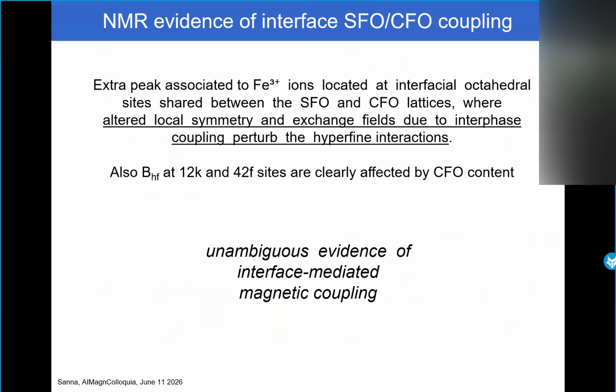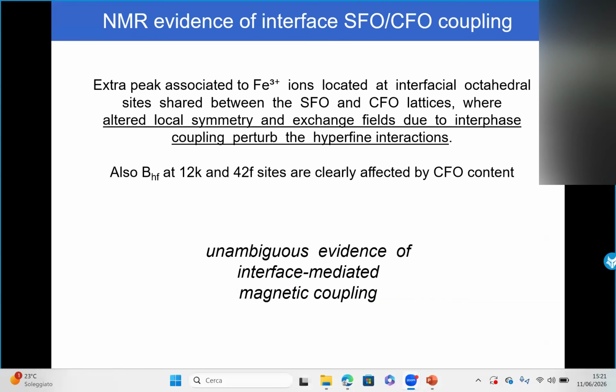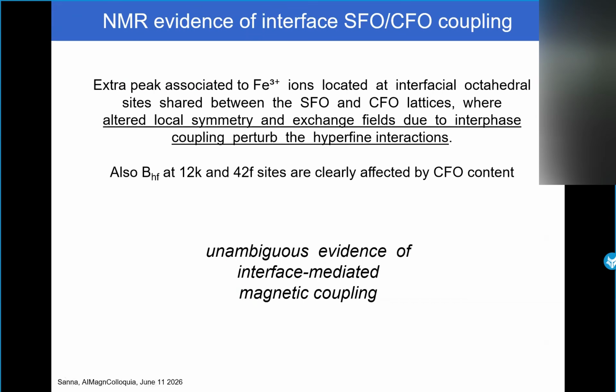So it means that this extra peak is associated to the iron 3 plus ions located at the interfacial octahedral sites shared between the SFO and CFO lattices, which alter the local symmetry and exchange fields due to the interface coupling, and which perturb the hyperfine interaction in the system.